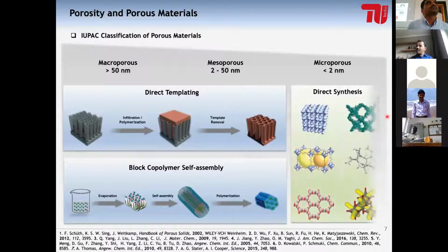But when it comes to the microporous region, where your pore size has to be just 2 nanometers, that is 20 angstroms, which is really hard to manipulate. In this case, the only leftover option to synthesize this material is direct synthesis. And what I mean by direct synthesis is, when you have to synthesize a microporous material, you have to coordinate metal centers with organic linkers to synthesize the materials with precise porosity.